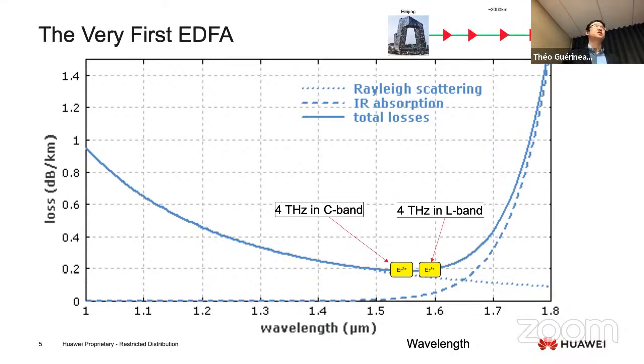This figure shows the transmission spectrum, the loss spectrum of the silica fiber. You see that in what we call the C band and L band, from 1.5 micron to 1.6 micron, the loss is the lowest. And luckily, the erbium emission bandwidth superimposes with this very low loss region. So 30 years ago, when the EDFA was invented, it could easily provide in total about 8 terahertz bandwidth, 4 terahertz in the C band and 4 terahertz in the L band. So this EDFA has served for more than 25 years.